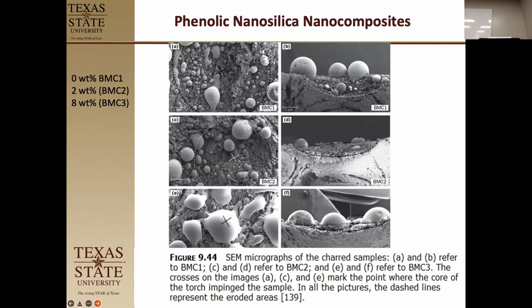So let's see. BMC1 is 0% nanosilica, and BMC2, which is the middle row here, is 2% nanosilica. They actually do a cross section of the ablation cone. You can see how far it burns down. We see a smaller ablation cone in the 2% loading of the nanosilica. And then this is a surface of the 8%. Notice that at 8%, there's a lot more melted material here, but there's also less ablation. So the nanosilica is changing the dynamics of that glass melting problem, getting it to improve its depth of ablation, at least.